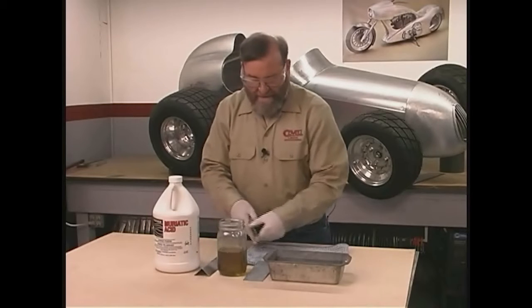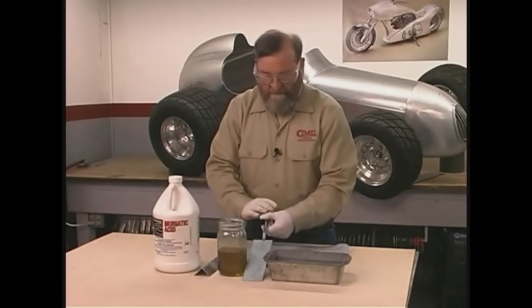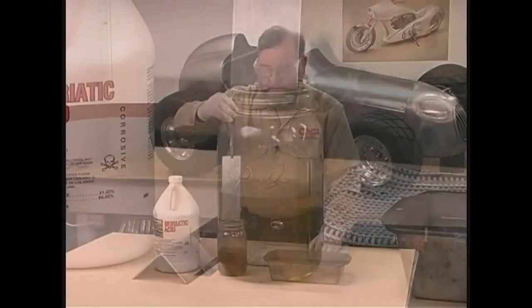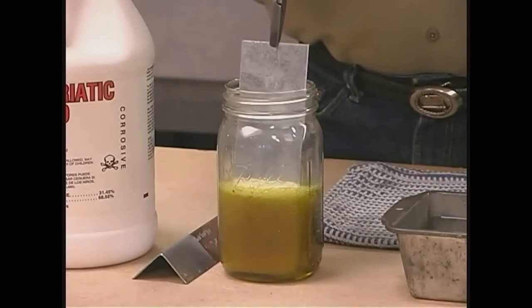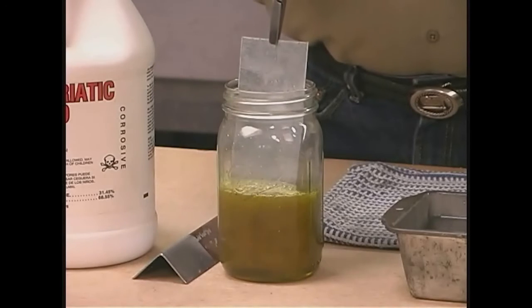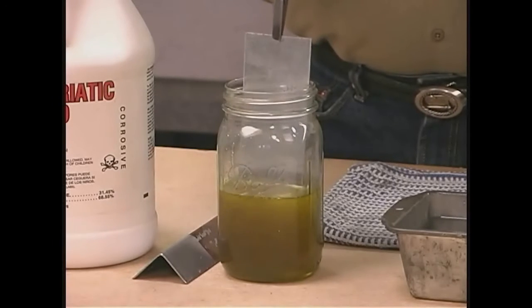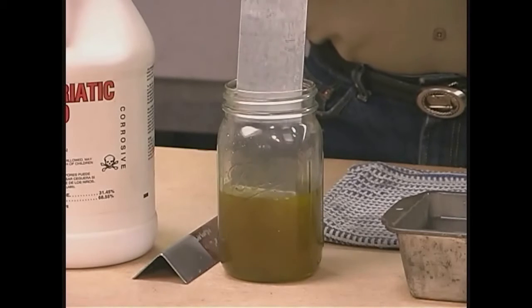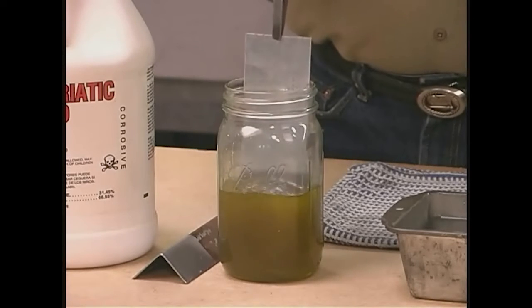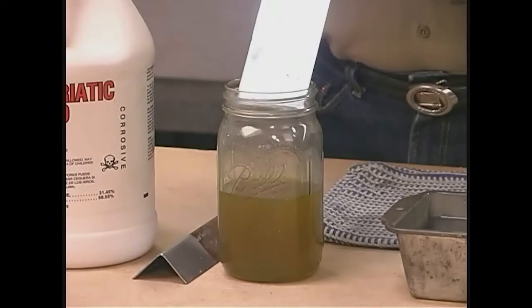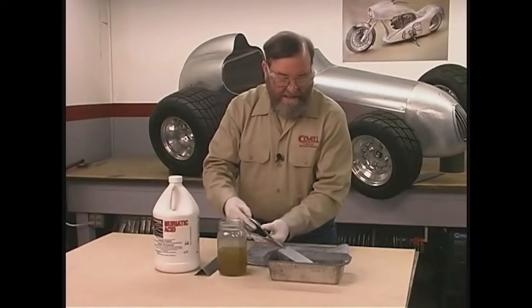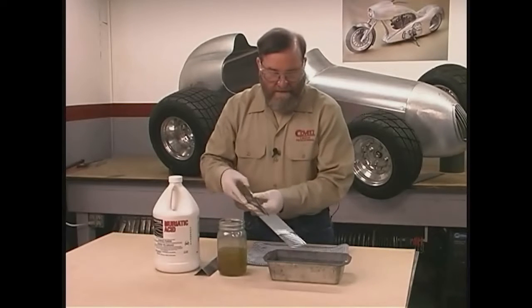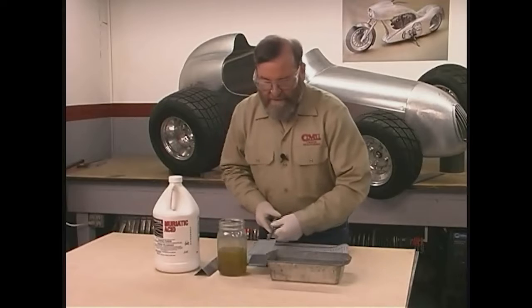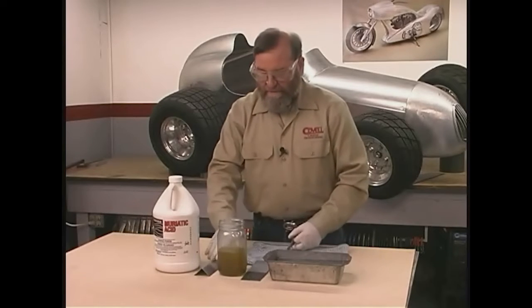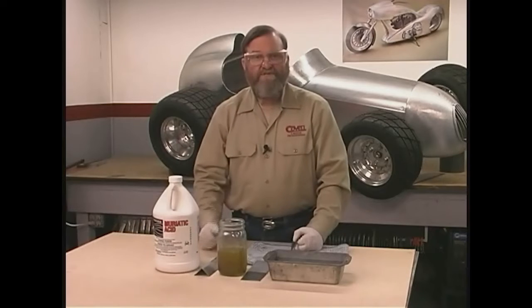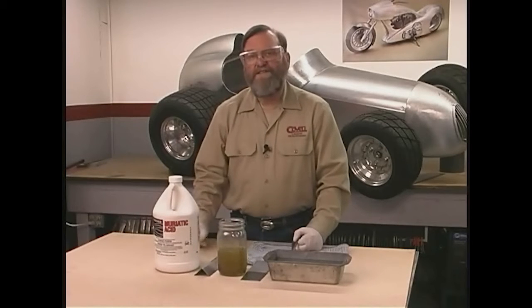And now let's do the galvanized piece. And you'll see the zinc starting to boil off the piece as soon as it goes into the acid. And this is where it's really giving off those toxic fumes. So again, I really recommend that you go outdoors to do stripping of this type. And again, I want to neutralize the acid by dipping it in water. So you can see that in just a few seconds, I've been able to strip both of these pieces. And they could be stripped with abrasives, but this is a much faster process.